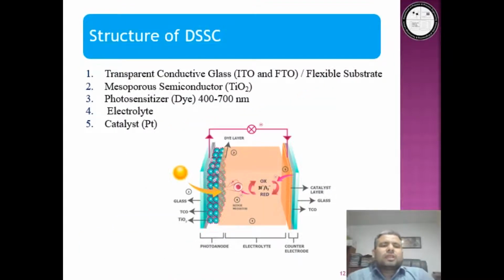As you can see, DSSC is traditionally fabricated using two sheets of highly conductive and transparent materials. Transparent glass coated with indium tin oxide and fluorine doped tin oxide act as a substrate. However, FTO is preferred because its sheet resistance remains constant upon sintering. Similarly, semiconductor metal oxides are used as photoanodes of DSSC. Its function is to absorb dye and transfer electrons to the external circuit. So titanium oxide is regarded as an excellent semiconductor due to good photocorrosion resistance and substantial electronic properties.